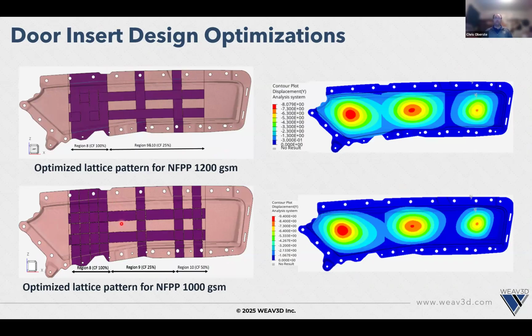And then we went even farther and we went to 1,000 grams per square meter. So in this particular one, the region 8 and region 9 reinforcements are basically the same as the 1,200 GSM, but we've added an extra tape in region 10 because there was a little bit of extra deflection here that we needed to reduce to get this within its target.